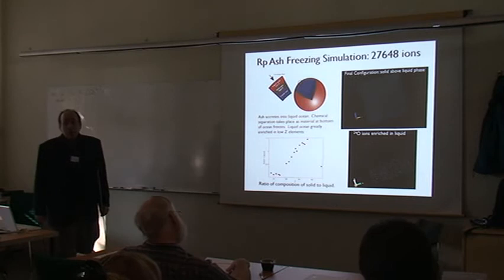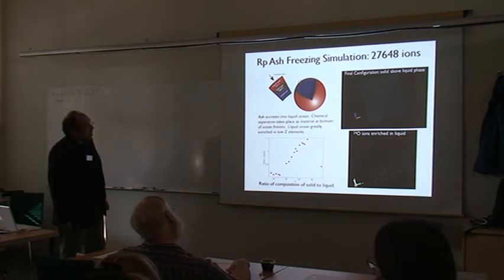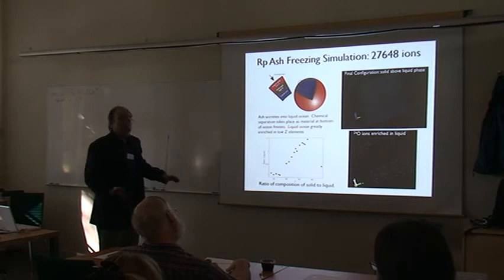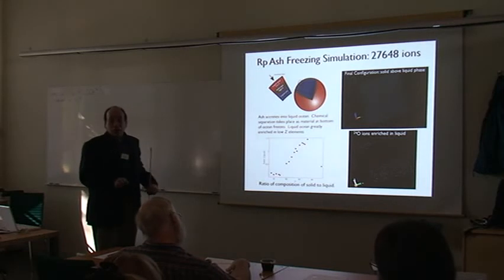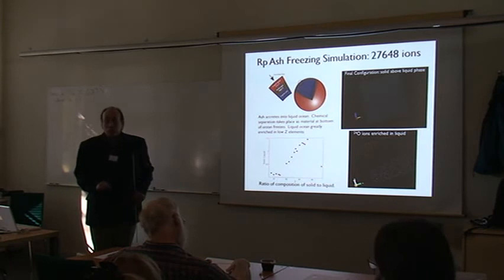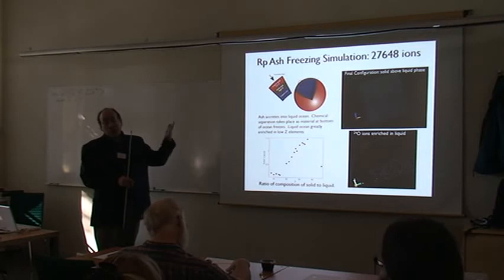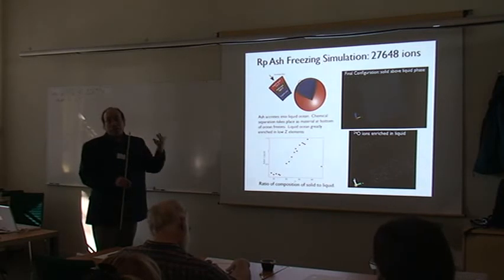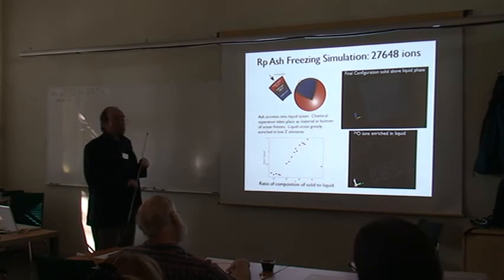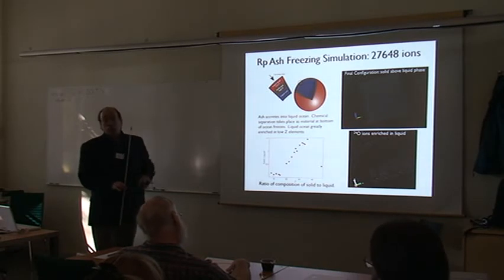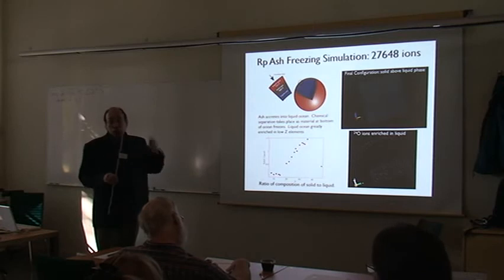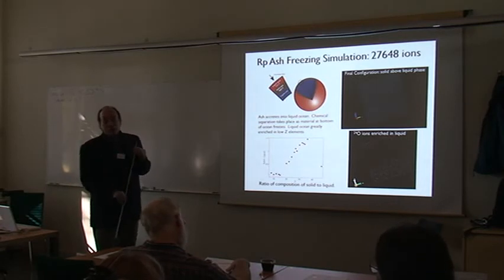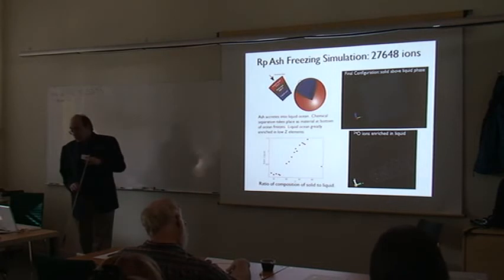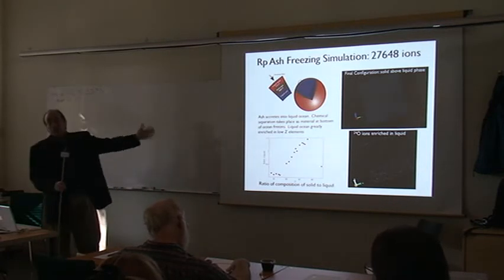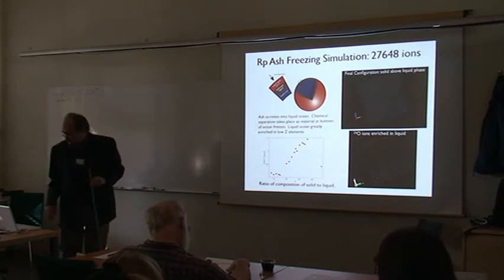What's the density where this is simulated? The freezing actually takes place at a density of around 10 to the 10 grams per cubic centimeter. It just depends on the Coulomb parameter, which is some ratio of density to temperature. But typically on an accreting neutron star, the star's a little warmer, so it freezes around 10 to the 10. So the outer crust is only a region between 10 to the 10 and a few 10 to the 11 in density.